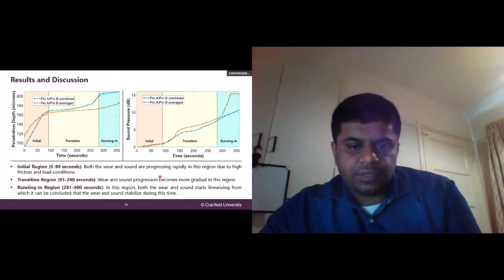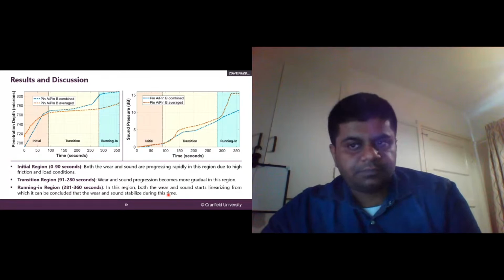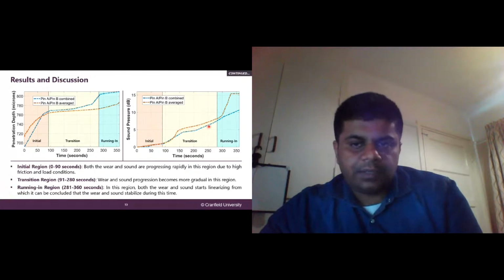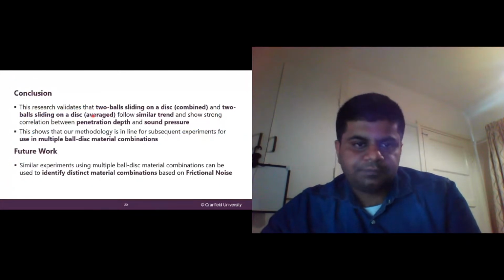In the transition region, the progression becomes more gradual. And in the running in region, both the wear and sound start linearizing, from which it can be concluded that the wear and sound are stabilizing over this time. So that is how these three regions are identified. The initial region is when the progress is more rapid, and when it becomes more gradual, you define that region as a transition, and the running in is when the sound and wear stabilize over time.